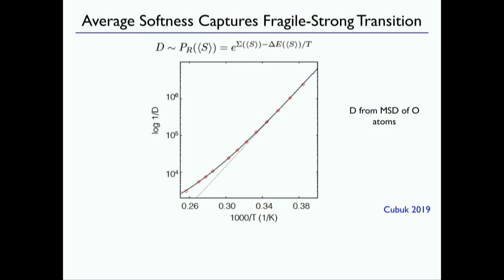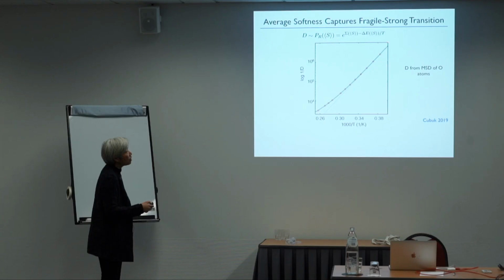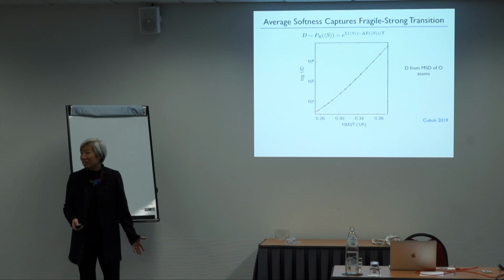And here what people measure is the diffusion coefficient of oxygen atoms. That's typically what they measure. Instead of relaxation time, they measure diffusion coefficient. And so we just make this same assumption. We say the diffusion coefficient should go like the probability of rearranging at the average softness. Put that in. The points are the measurements of the diffusion coefficients, and the curve is our prediction. It's beautiful. It really works.